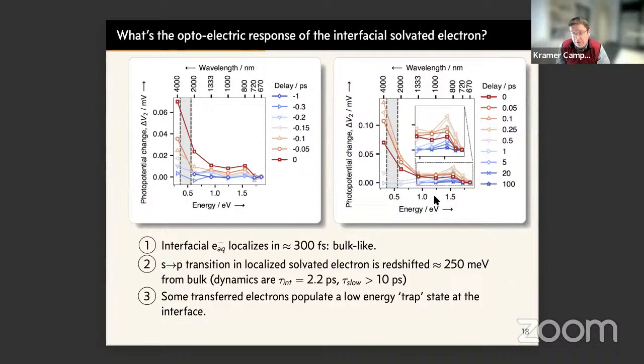If you now go past 0 to positive times, so now we move to the right-hand panel, what's apparent very quickly, qualitatively, is that as you go to positive times, first this absorption at long wavelengths, in the first, say, 100 femtoseconds or so, grows in, but then you rapidly lose intensity here and instead gain some intensity at, say, around 800 nanometers in wavelength. So this is what's shown here.